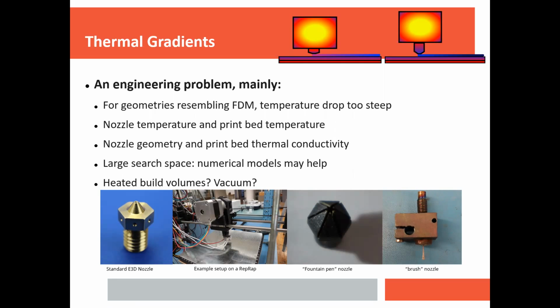Generally speaking, if you have a long nozzle, it cools off quickly and your material solidifies before it gets out of the tip. Unlike with thermoplastics, the metal has a very high thermal conductivity, and that temperature drop is extremely steep. And the change in viscosity with temperature can be much faster than in a thermoplastic. So all of that, plus the granular jamming issue, means that you need to make sure that nozzle remains hot enough that the metal can actually get out of the tip and not jam. So that's the main issue there.